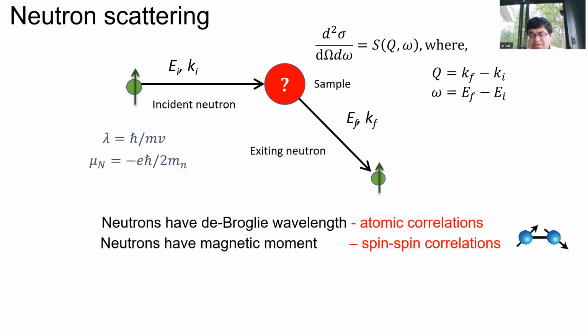But another very important property which neutrons have, which makes it so special, is that they are chargeless. That's important because if it was charged like electrons, then it basically goes into your material and then changes the band structure. And it doesn't interact with the electrons directly, unlike X-rays, which also kind of starts to excite the system. So neutrons are pretty forgiving from that standpoint because they are chargeless, but they have a spin.